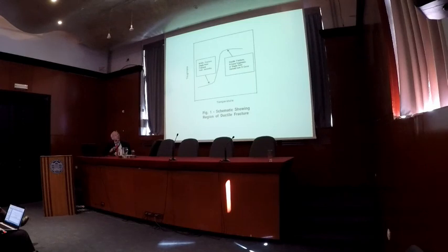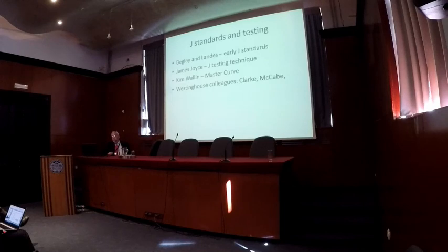Now, in fracture behavior, particularly in steels, and steels are quite useful yet, even though people look at new materials in a lot of cases, but steels can be useful. At the low temperatures, you get essentially low fracture toughness, so the K works pretty good here. But at the higher temperature, you go through a transition and you get very high toughness, and you can't characterize that by K anymore, you need the J.